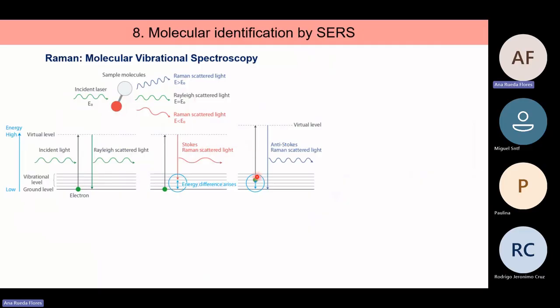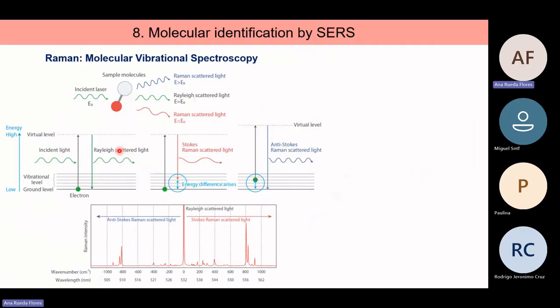But you can have the other situation. You can start with an excited state. With the illumination, you go to the virtual level, and then you can decay to a deeper state. So at the end, what you have in the Raman spectrum are peaks well located at given positions that depend on the transition between the vibrational states. So a Raman spectrum is a fingerprint of the existence of a certain molecule.